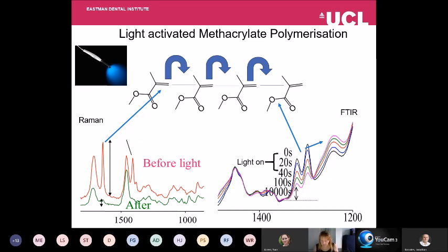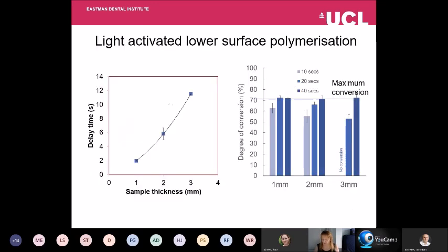What these results are showing is that when we turn the light on, we get very fast reaction, very fast loss of the methacrylate peaks. However, when we turn the light off, the rate of the reaction slows down. With infrared, what it's also possible to do is look at what happens if you have samples of different thickness.